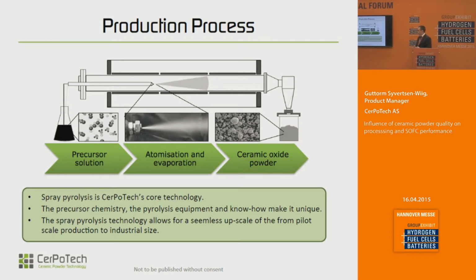So the core of our business is the spray pyrolysis unit, our workhorse. It starts out where we are dissolving different elements in water, stabilizing this, and often adding some secret ingredients to make sure you have a stable solution. Because if you have some precipitation, you don't end up with a phase pure powder in the end, and you have no control. Then this solution is sprayed through the chamber and collected and dried, and the powder is collected at the end. And here you have a large number of parameters you can vary to tune particle size, surface area, and so on.